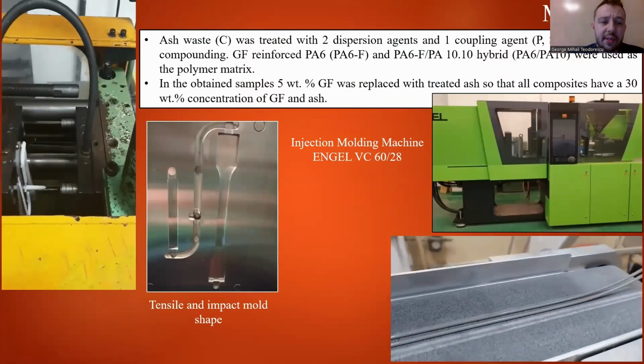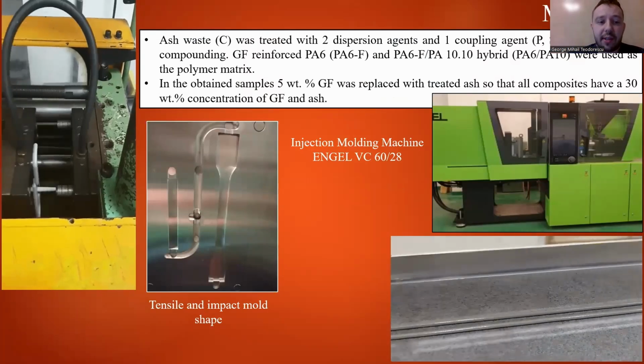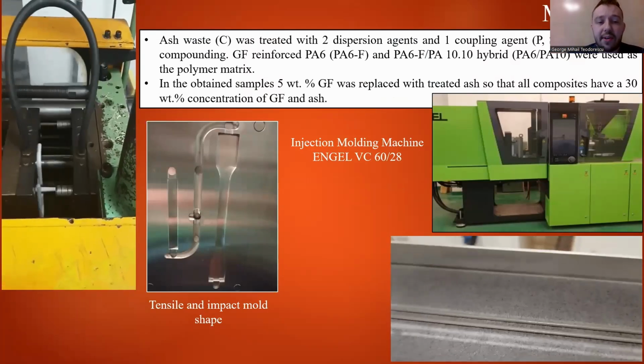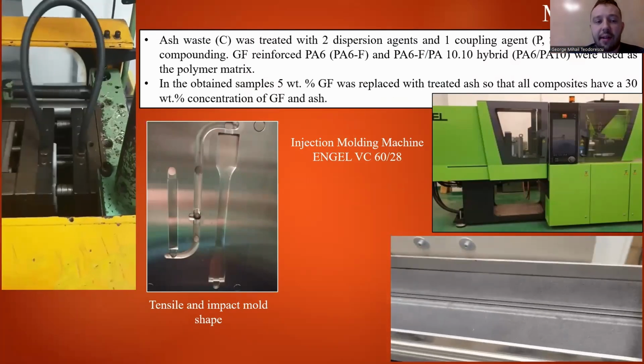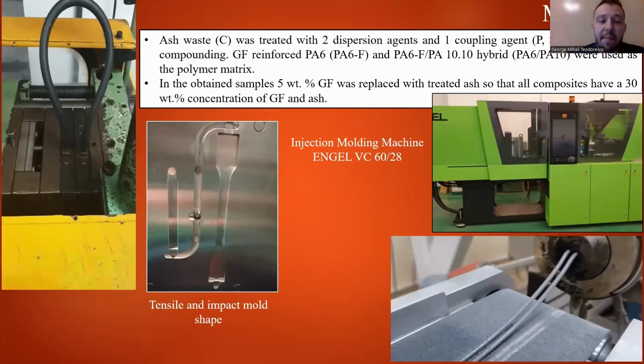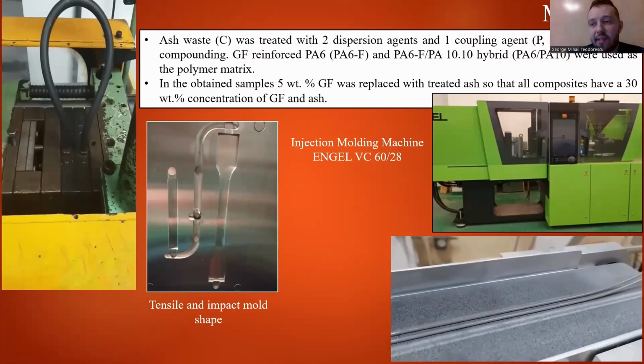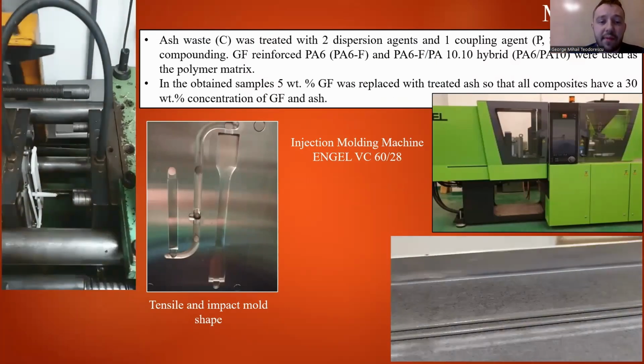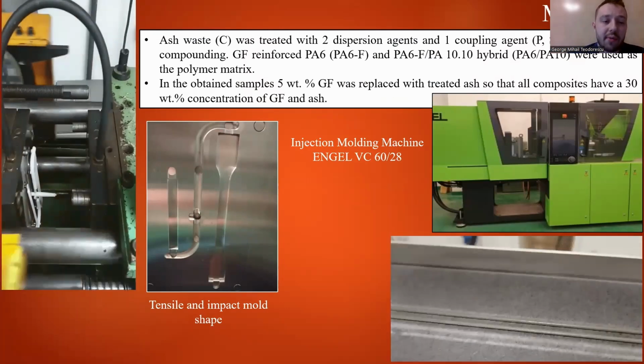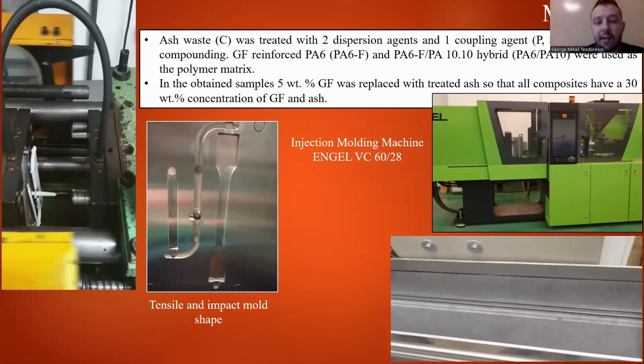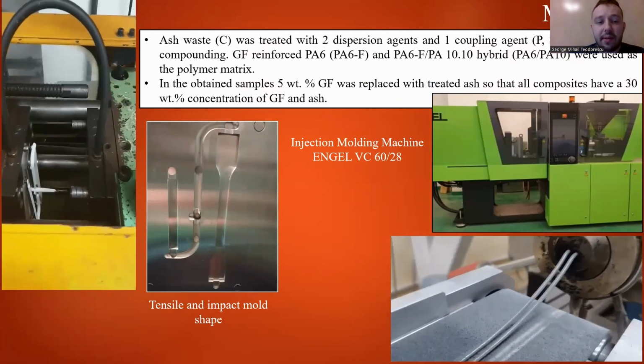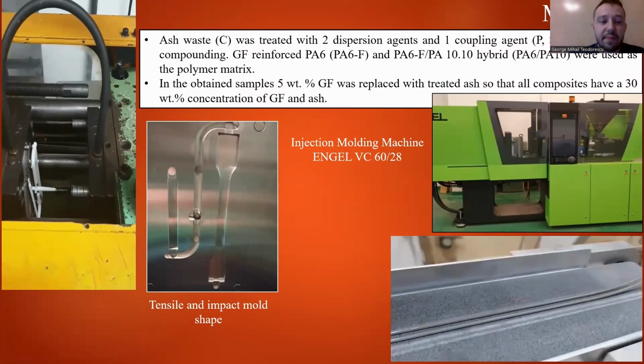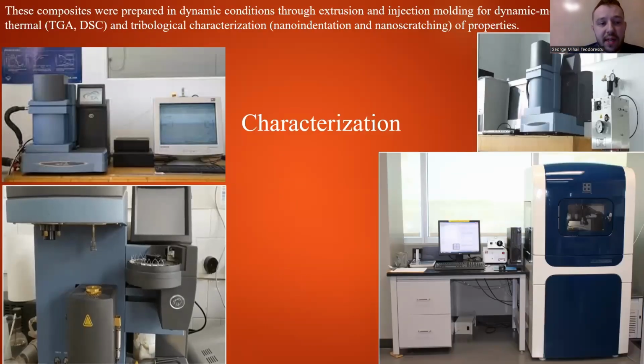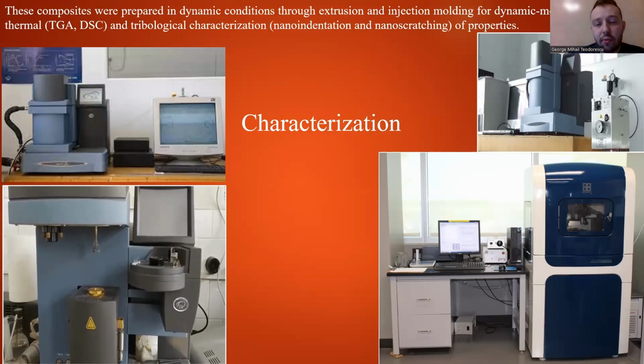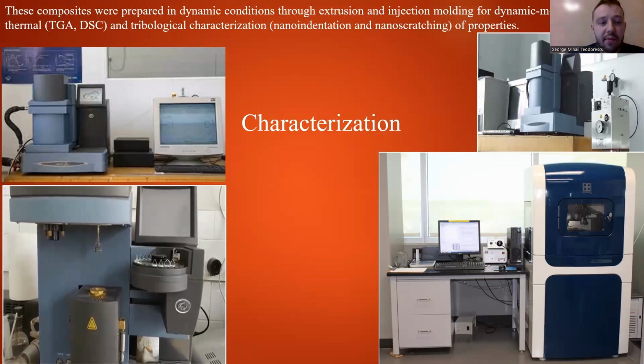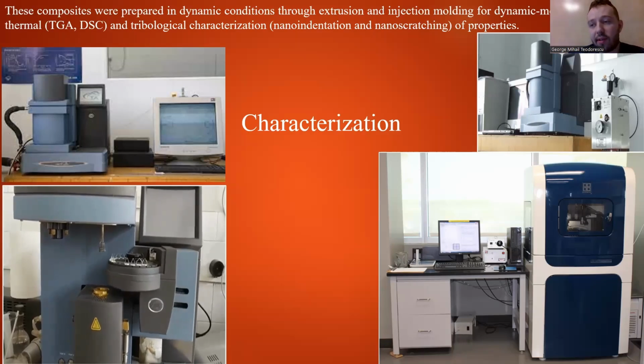Fly ash was treated with 2 dispersion agents and a coupling agent, a polyester diol, a metal salt of a fatty acid, and a silane. By melt compounding and in the obtained samples, 5% of the glass fiber weight was replaced with treated ash, so that all composites have 30% concentration of glass fiber and ash. And the composites were prepared in dynamic conditions through extrusion and injection molding for dynamic, mechanical, thermal, and tribological characterization of properties.